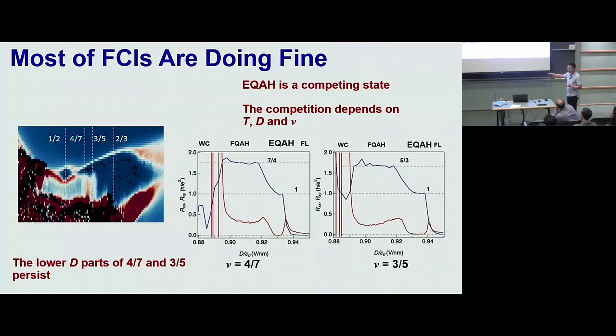They are still FCI. So there's clearly competition between what we call this extended quantum anomalous Hall state and FCI, and that competition depends on temperature, displacement field, density, and the current. Even at the base temperature with the smallest current that we can use to measure, if you do a line cut like this at 4/7 and 3/5, you still have the majority of the FCI being there, although the higher displacement field part develops an integer plateau that corresponds to this little triangle here.